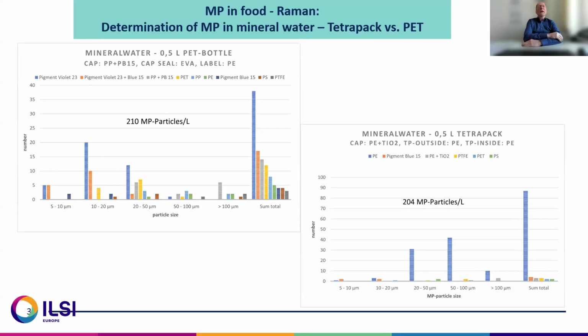Then we compared, from another process line, a PET bottle with a Tetra Pak. And you can see that the content is nearly the same, around 200 particles. However, here it is also the same that in the PET bottle 70% of the particles are again pigments, and not so much polymers. In comparison, in the Tetra Pak there is no or a very low content of microplastics and a very low content of pigments, and we only found polyethylene. But the outer and the inner shell of this Tetra Pak and also the cap are made of polyethylene.